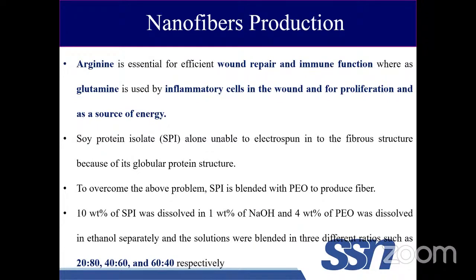When we searched the literature, we found that soya protein isolate, the extract obtained from soya bean, is rich in arginine and glutamine. We thought of utilizing this property in a wound dressing material, right? So we started electrospinning soya protein isolate. What we observed is that we couldn't convert this polymer into fibers because of its globular structure. Whenever we did electrospinning with SPI, it was just splitting the polymer. We were just getting beads, because of its globular nature.